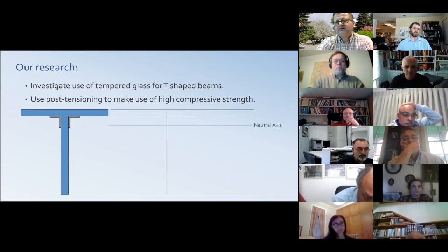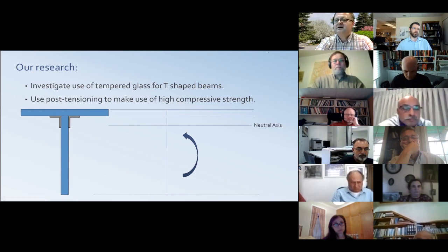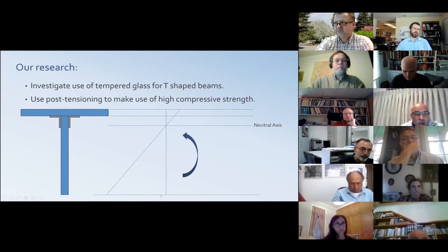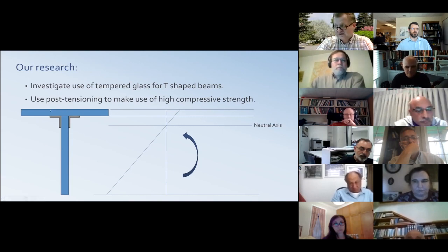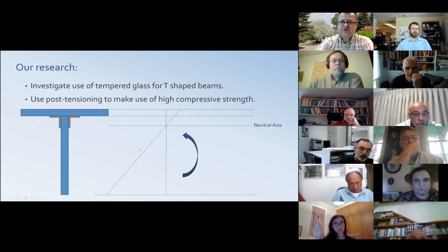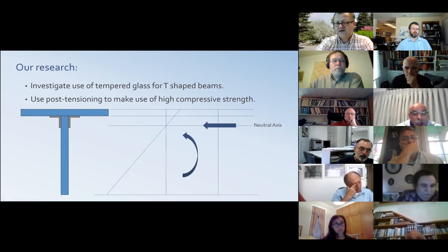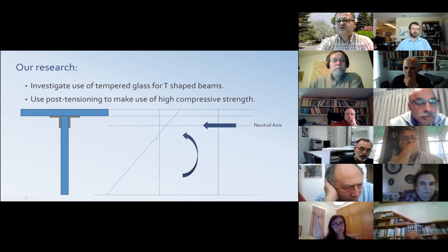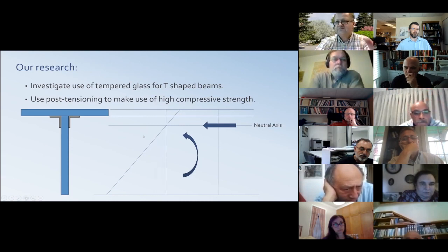So when you have a beam like this, and when you apply bending around the neutral axis, you get compression on the top and tension at the bottom, which is not very desirable, because remember, the tensile strength is in the order of 50 to 120 megapascal. The compression strength is high. So there's a trick that we use in reinforced concrete structures, where we apply an axial post-tensioning or pre-tensioning. Since glass is already manufactured, we apply a post-tensioning. And then we just bury this field of compression further into the material and reduce the tensile stresses. So that's the theory behind it.